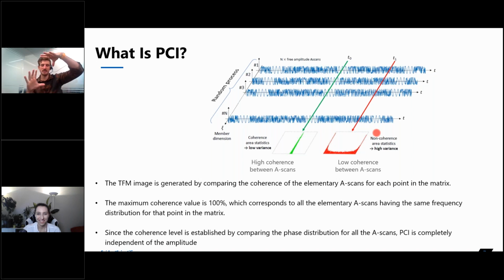So if we have our box for a TFM image, at every point in the box, rather than adding all the amplitudes together, we're going to take all of our n A scans, look at that point in our box, and do a statistical analysis between all of the A scans. The closer the frequency distribution of our A scans is, the more likely we can say that there is a defect at that point. Because where there's a defect, all of the frequencies are going to be very similar and have a very small distribution, whereas where we have just background noise, the distribution is going to be random and they're not going to be similar from one A scan to another.